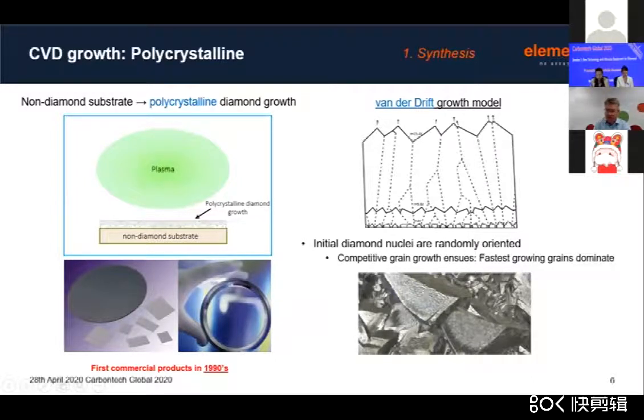And this leads to a polycrystalline material with many properties very similar to single crystal diamond. It can have similar optical absorption properties, especially in the infrared. It can have similar thermal conductivity as single crystal diamond, and in some applications it can have enhanced mechanical properties, and it's a little bit easier to dope for electrochemical applications.